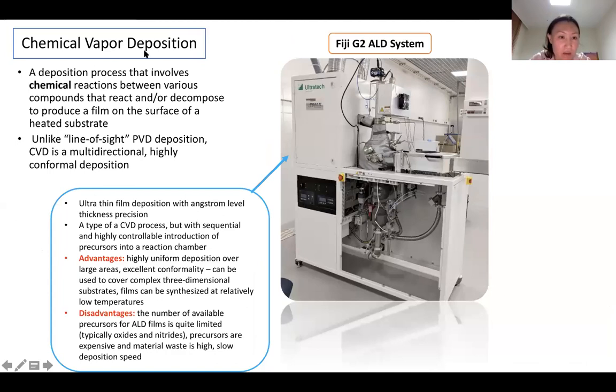Okay, now the chemical vapor deposition. Chemical means there are some chemical reactions acting. This tool is called atomic layer deposition. From the title, we can say that the material can be deposited as thin as one atomic layer, right? So we will have thicknesses starting from several angstroms to nanometers. This is especially useful to deposit dielectrics, for example, zinc oxide, aluminum oxide, hafnium oxide. But this is quite a complex tool, and it requires special gases like precursor gases. Also, precursors are expensive, and they require very careful maintenance.